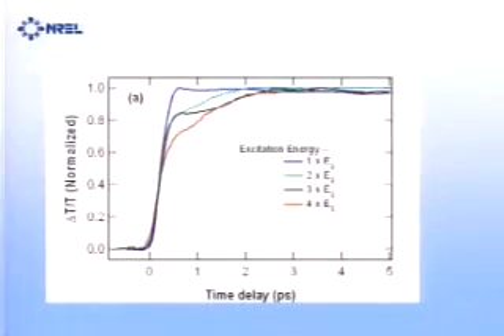And so we did the time-resolved transient absorption to look for this. First, it just shows exciting at the band edge. You just get the fast rise due to the instrument-limited response because you create the electron and hole right at the 1s, or the HOMO-LUMO, so you'll see the full bleach immediately.